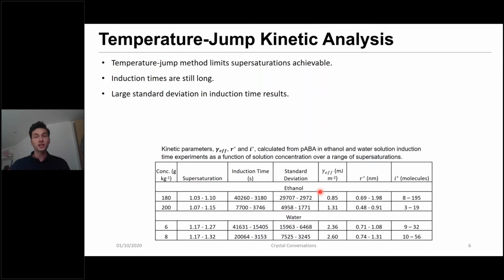So the time it takes, this induction time, can range dramatically for the same system under the same conditions. And this has led to the use of probability distribution functions to determine accurate information from induction times. But it is quite a high throughput experimental method. You need at least 80 repeats to get accurate data about the probability.